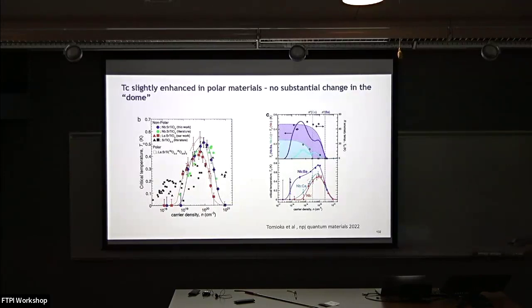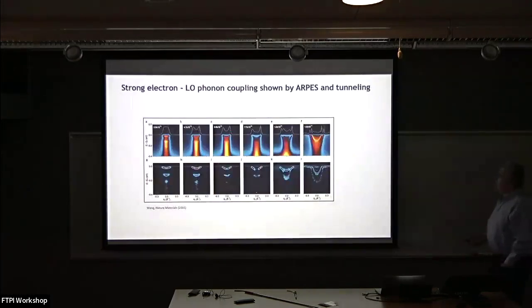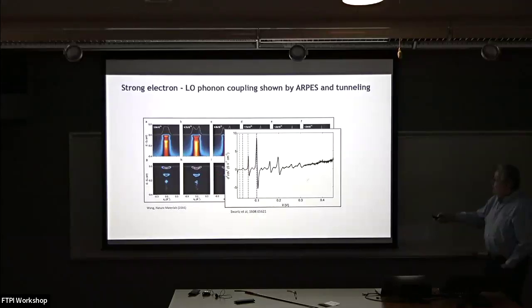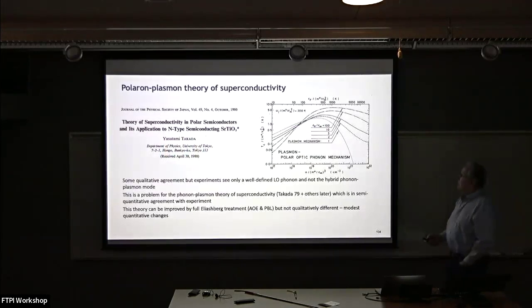Some more data. There's now a lot of data associated with different materials, some of which are actually polar. And the basic message of that is that this dome with carrier density doesn't really care whether you're on the ferroelectric side. There is strong LO-phonon coupling. And so this you can see, and so these are LO modes and numbers of shakeoffs. So this is from Planck's group, this is from photoemission. So we know that that coupling is strong.